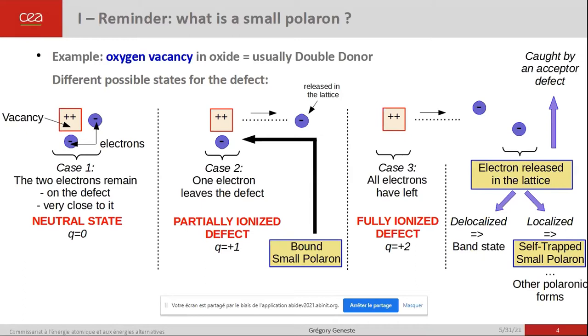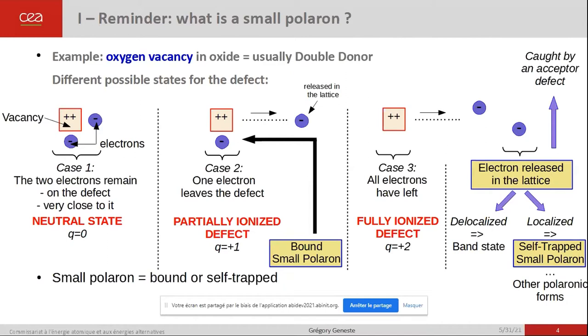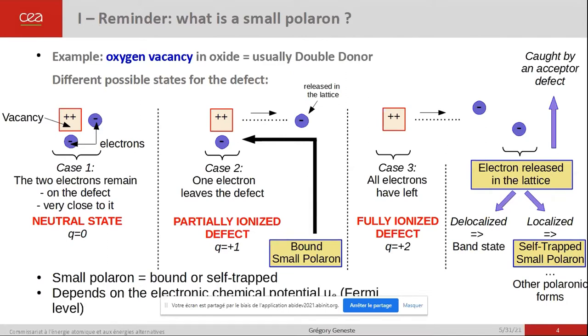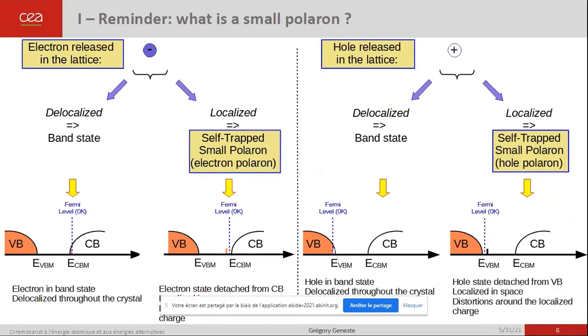Note that the electron localized close to the defect in a partially ionized or neutral state is sometimes denoted as a bound polaron. The small polaron can be bound or self-trapped when it lies far from any defect. The state in which you find the defect depends on the electronic chemical potential, that is to say the Fermi level. The electron can be either delocalized in an extended state at the bottom of the conduction band, or localized as a self-trapped electron polaron, occupying a quantum state lying in the gap, detached from the conduction band.